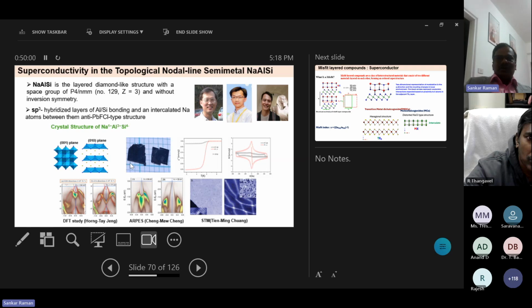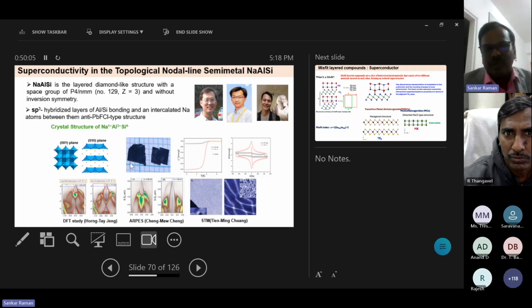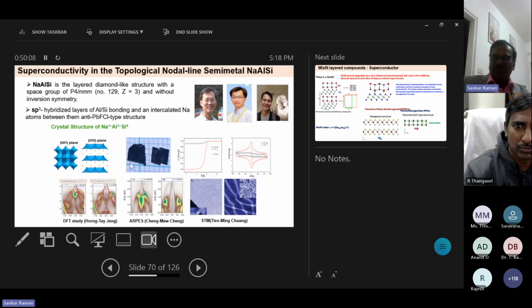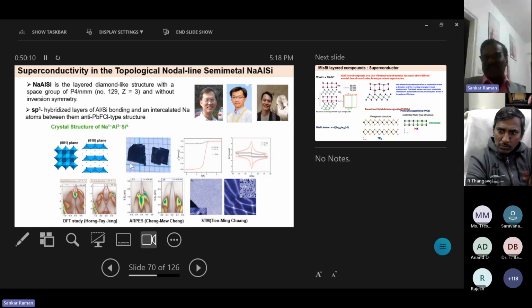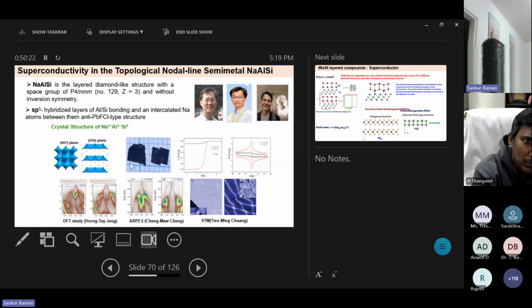Another topological nodal line material is sodium aluminum silicide. People have never heard of it, because mostly we hear that silicon has a 4+ valency, right? But in this case, silicon has a 4- valency. Aluminum and silicon coordinate to form a layer. In between the layers, we have sodium. The sodium content decides your superconducting transition temperature, because you can tune the transition with respect to sodium content. Another thing, we cannot use this sample easily.